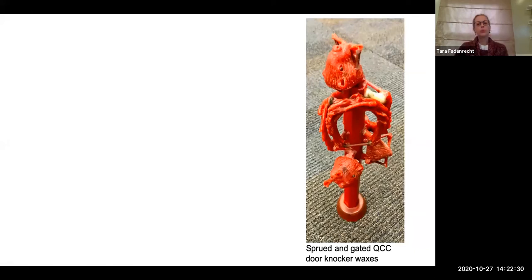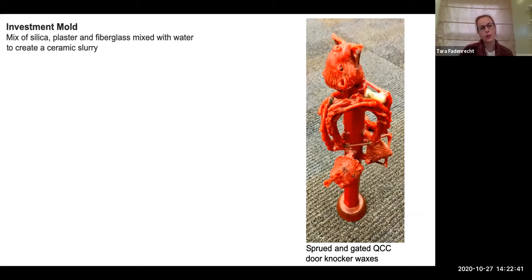All of these components coming together to help us achieve the successful casting on the end. So gating and spruing is extremely important. It doesn't matter how fantastic your wax is if you can't get the metal delivered to that part of the mold. The particular type of refractory material that we work with is a mix of silica, so sand, plaster, and